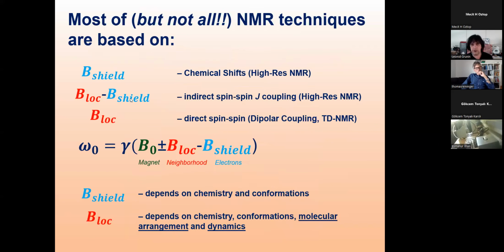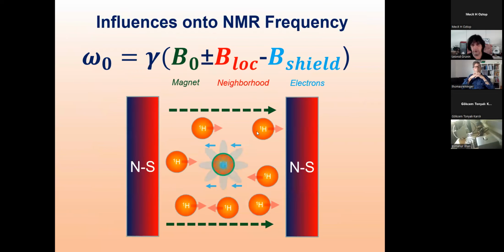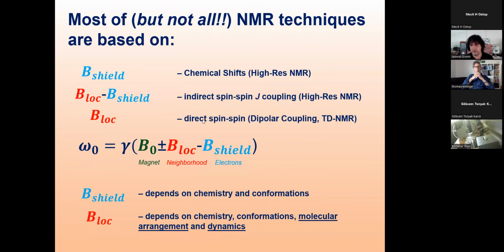Well, let's look. This shielding field, as I already mentioned, is from electrons, and we call it chemical shift in high resolution NMR spectroscopy. We will not talk a lot about that. There are also some other types of interactions, like indirect coupling. For us, it's more important that this direct local magnetic field from the neighbors is called direct spin-spin, or in other terms, dipolar interaction, dipolar couplings. This is the main reason for time domain NMR. And this local field depends on chemistry, molecular conformations, molecular arrangement, and also on dynamics. If they move, the field also changes, but they always move.